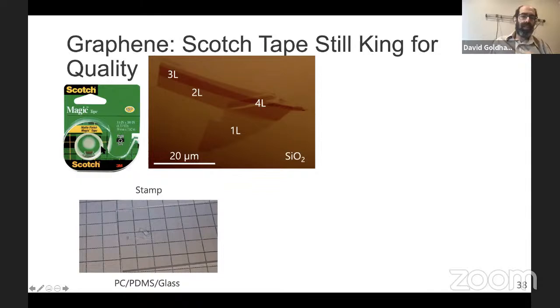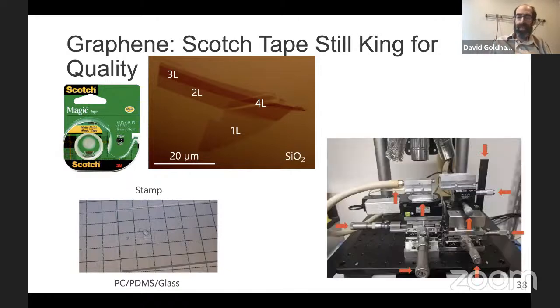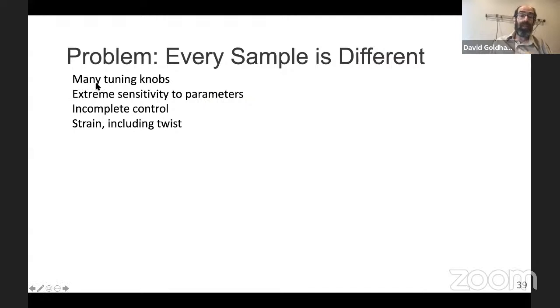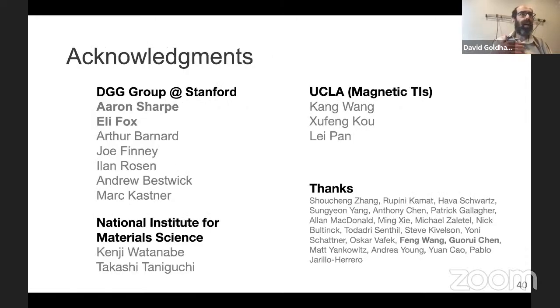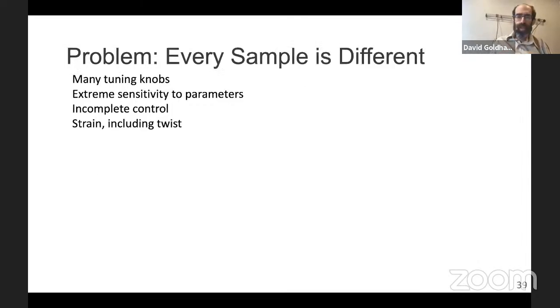Traditionally Scotch tape is used, ever since Andre Geim's work with Kostya Novoselov, to peel off monolayers. You get random flakes, and then you pick them up in a stack with a stamp. And this is a picture of our stacking system. And there's a lot of control, but a lot of randomness in this. And that means that every sample is different. There are many knobs that we know are important, and probably ones that we don't know are important. There's sensitivity to even hundredths of a degree of twist, and strain we now believe is also important, including uniaxial strain. And so tomorrow I will tell a story of one of our attempts to reproduce this magnetism and what we found instead, which was again very interesting.